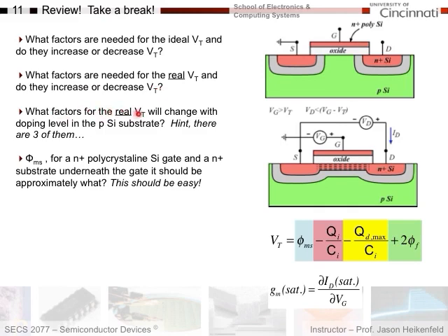Of these factors for the real threshold voltage, which ones will change with doping level? So if you look at the whole equation here, of these four terms, which ones will change as I change doping level in the P-type substrate? The hint is that there are three of them that will change, and one will not. Last one, Phi sub MS. This term out front. For an N plus polysilicon gate and an N plus substrate underneath, where you get the doping levels to be almost equal between the gate and the substrate, what will Phi sub MS be approximately? This should be really easy if you remember the argument we had from the previous slide on it.